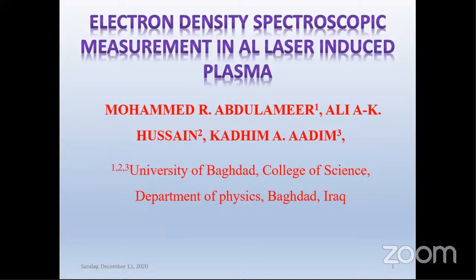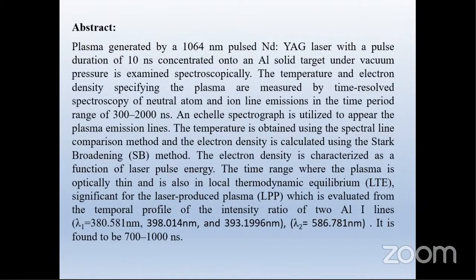My research is electron density spectroscopic measurement in laser induced plasma. Abstract: plasma generated by a 1064 nanometer pulsed neodymium YAG laser with a pulse duration of 10 nanoseconds, concentrated onto an aluminum solid target under vacuum pressure, is examined spectroscopically. The temperature and electron density specifying the plasma are measured by time-resolved spectroscopy of neutral atom and ion line emissions in the time range of 300 to 2000 nanoseconds.